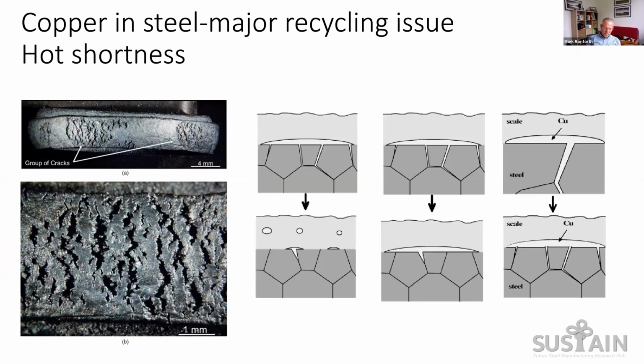Okay, so that was the first example. The second example is looking at copper in steel. And there are obviously ongoing projects about reducing the level of copper in steels. Copper is very detrimental, for example, in terms of hot shortness. So you have an image here of where you have hot shortness cracking. And I won't go through the mechanisms of this, but it's clearly associated with copper.